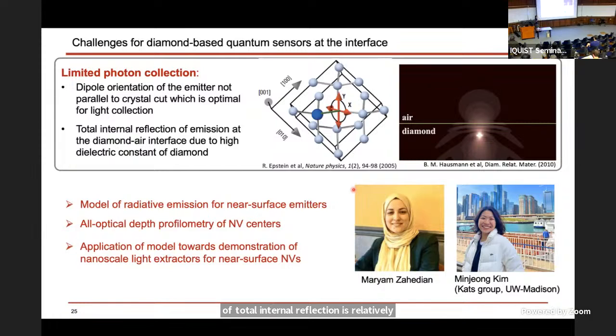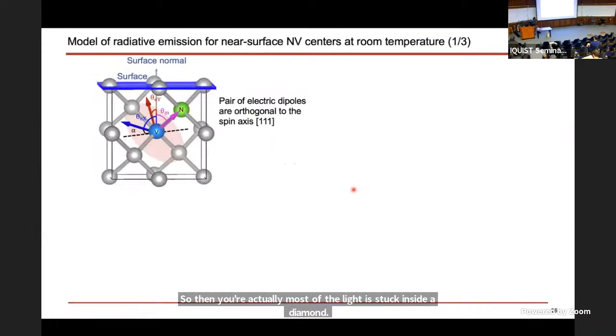So then most of the light is stuck inside a diamond crystal. So first, I want to talk about how to properly understand this emission behavior. The spin defects in general consist of electric dipoles that are orthogonal to the spin axis. So the emission that you get from color centers is not from dipole emission along the spin axis, but basically from the direction that's perpendicular to it.